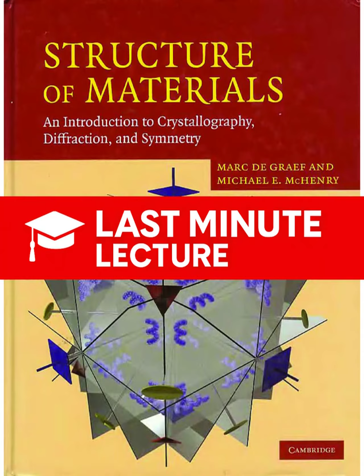It does. If two waves scattered from adjacent atoms travel slightly different distances, that path difference, delta, dictates the phase shift. We calculate the phase difference relative to the wavelength. And constructive interference, a bright spot, only happens when that path difference is an integer multiple of the wavelength. Right, when delta = nλ. Any other path difference leads to partial or total cancellation. The crystal acts as a selective filter, only scattering intensity in very specific directions where this phase condition is perfectly met.